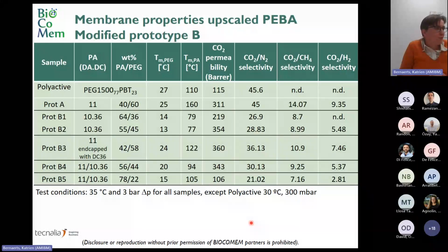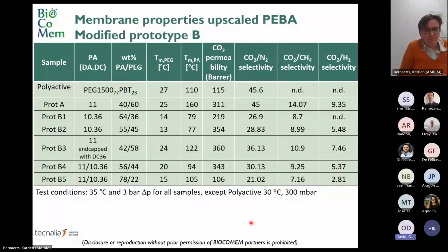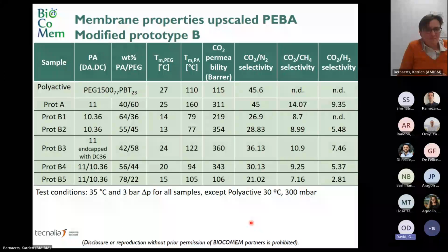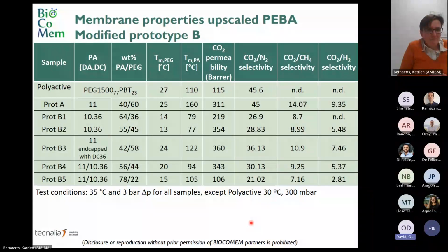And we compare it also with some reference polymers. Okay, so the first line is for PolyActive, which is another type of block copolymer that has a polyethylene glycol part and a polybutylene terephthalate part, the other block. And it's used to make thin film composite membranes. So we took these values for carbon dioxide permeability from literature.